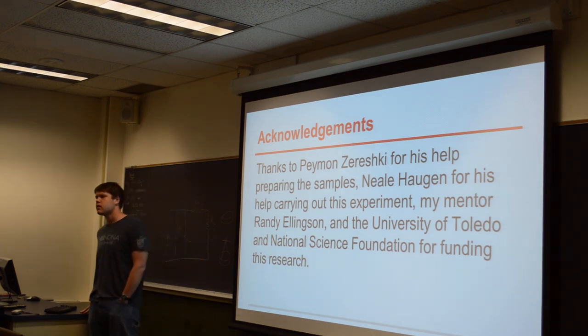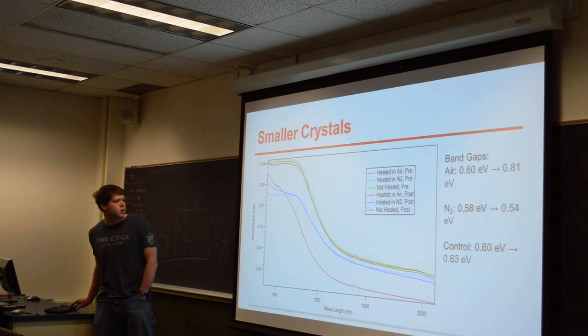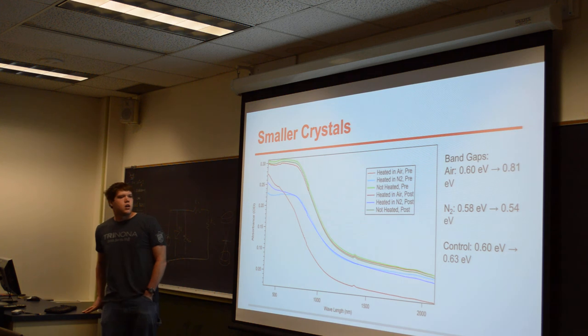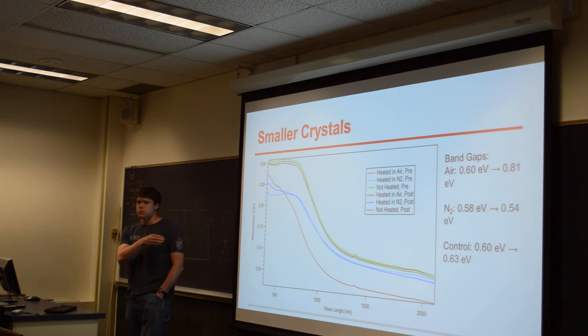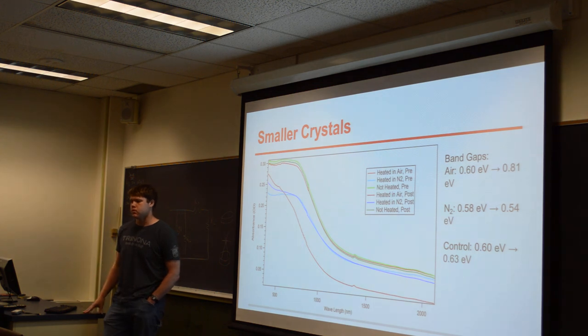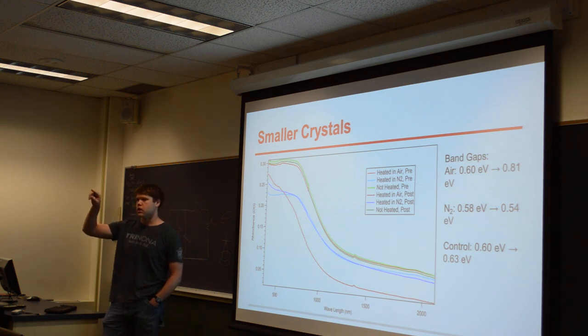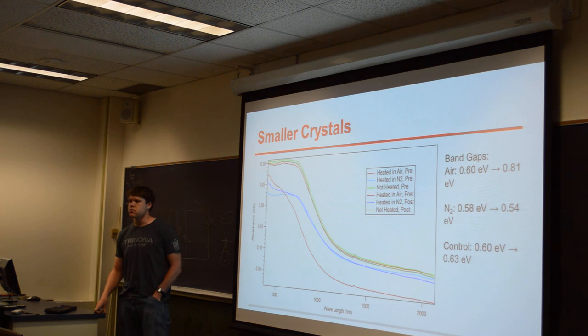I have a couple of questions. First question is: how did you determine the band gaps? I took the energy multiplied by the absorbance, took the square root of that, plotted over the energy — that gave a function with a couple of linear portions — and basically extrapolated the line from the first linear portion on that plot to find where it crossed the axis, and took that energy as the band gap.